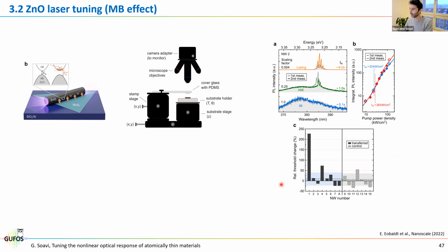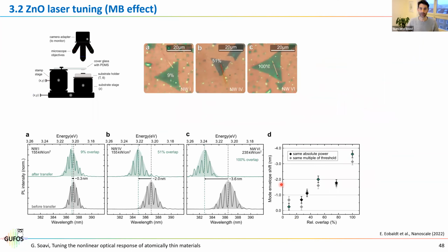And now since we can do that, we can use this method to transfer the nanowire on top of the TMD. The first thing that we tried, a very simple approach, was to change the overlap between the nanowire and the TMD. What you see here is that we move the nanowire farther and farther until it completely covers the TMD. At the beginning, we start with a 9% coverage, and then 50%, 100%, and different values.